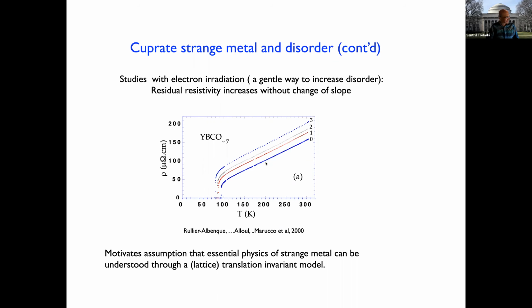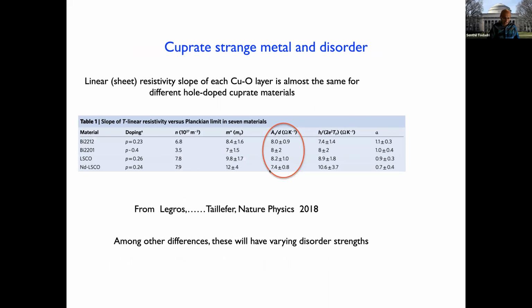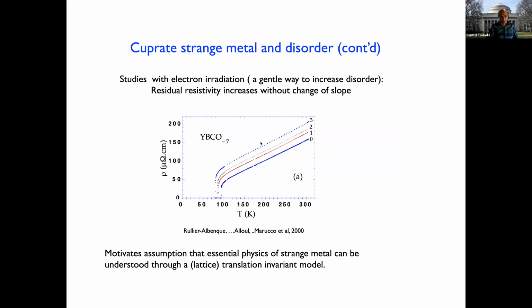It's not just that the slope is insensitive. That combined with my previous observation, these two, seems to tell you that the slope is insensitive across different samples to, among other things, the level of disorder. And here, in the same sample, it's insensitive to the level of disorder, right? So all of these motivates the assumption that the essential physics of the strange metal can be understood through a lattice translation invariant model, okay? Even if in real life, there are impurities, you can worry about impurities as a correction to the essential physics.